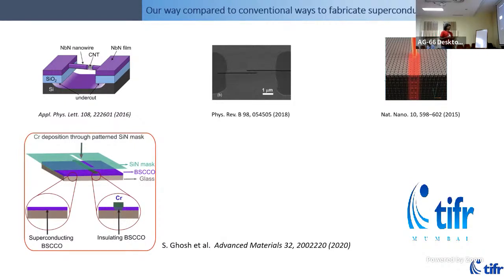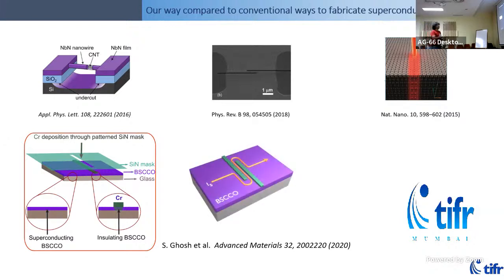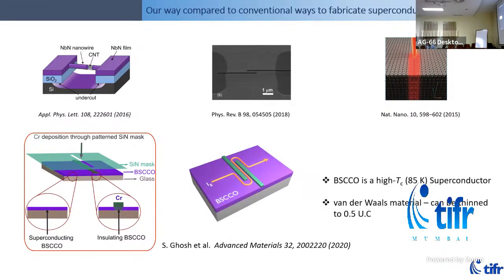So 2 years ago, we figured out a way to modify the superconductivity, which is essentially, the easiest way to describe it, to pattern wires. You do a kind of a rangoli of chromium atoms. So you deposit chromium atoms using a rangoli mask. So it's a stencil mask. When the chromium atoms land on the superconductor, they kill the superconductivity underneath it. And so you basically can make complex structures. You start with a purple colored BSCCO thin layer, and I'll show you quickly how it works. Then you put a stencil which deposits green chromium atoms, so you automatically make very narrow wires which are only a few atoms thick.